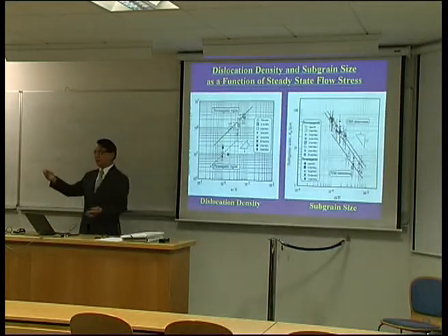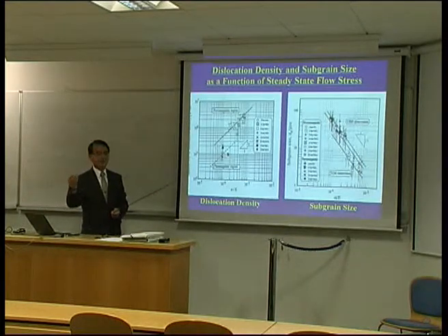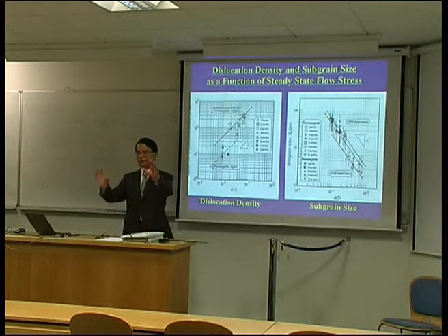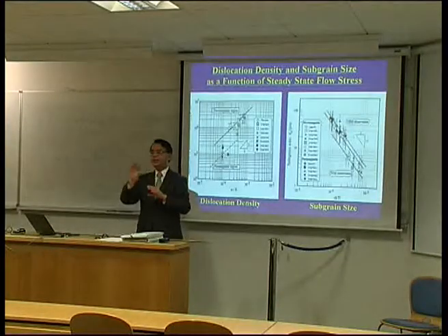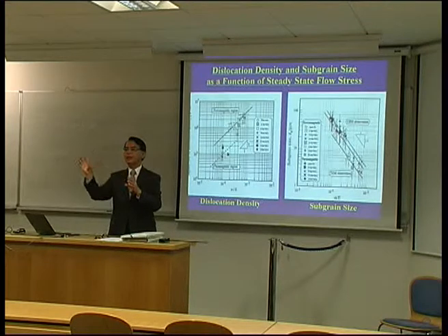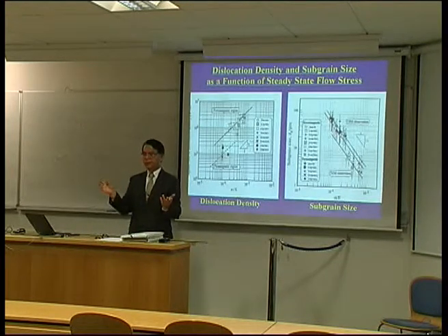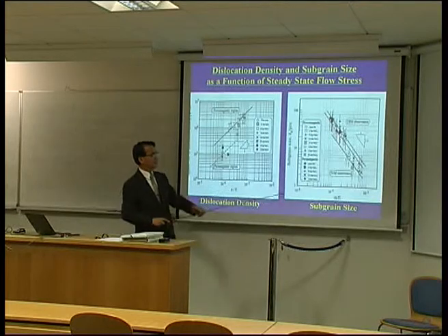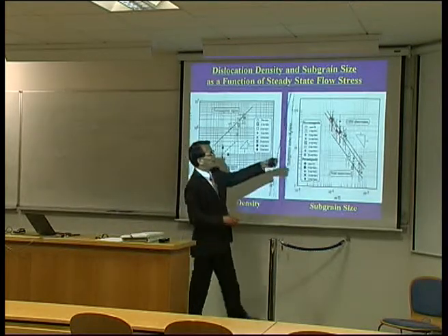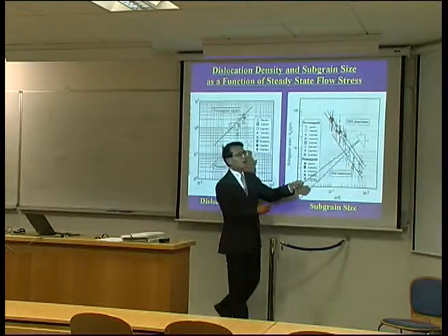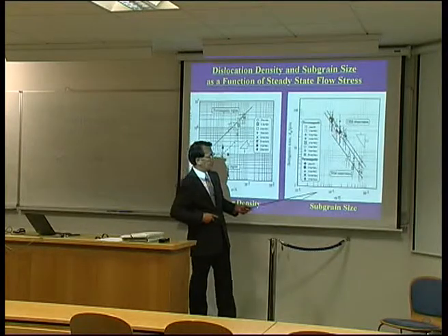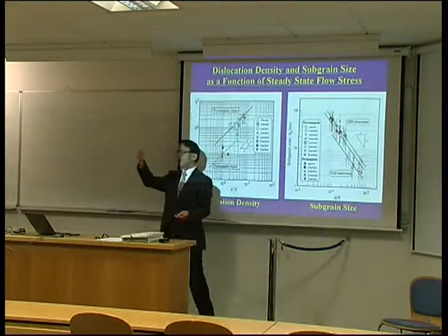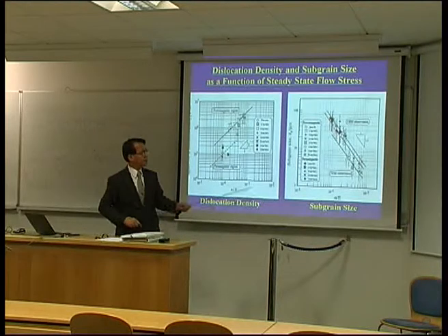For example, if some of you are interested in the microstructure in deformation, of course, during high temperature deformation, dislocations form a cell boundary, and then the misorientation can change. So the cell boundary affects the dislocation motion, and the formation of the cell boundary is very important. So how can the cell size change as a function of stress? Normally, there is an almost inverse relationship. With increasing stress, the cell size decreases, of course, since the dislocation density increases at the higher stress level.